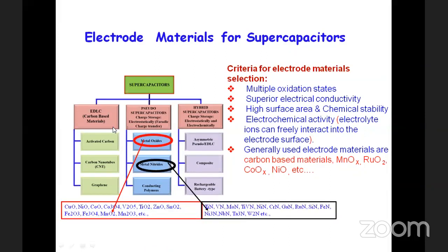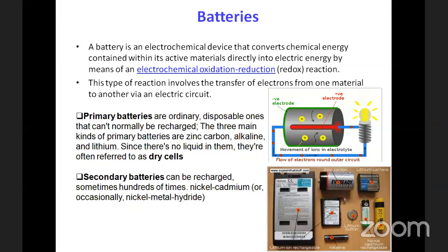If you talk about metal oxides, there are a variety of them like copper oxide, nickel oxide, cobalt oxide, manganese oxide, and so on. And for metal nitrides, many researchers worldwide have reported on titanium nitride, vanadium nitride, molybdenum nitride, gallium nitride, and ruthenium. In fact, ruthenium and the ruthenium family have been showing very excellent supercapacitance. If you see through the literature, unfortunately, the cost of such materials, pure ruthenium, is very high. Therefore, people are trying to synthesize oxides and nitrides at much cheaper rates through PVD and CVD methods. I will not go into the topic again in detail.